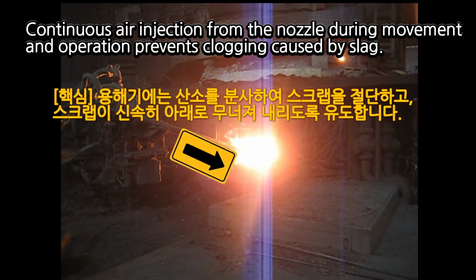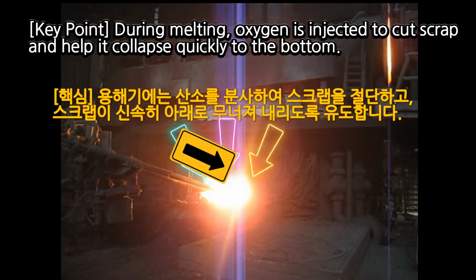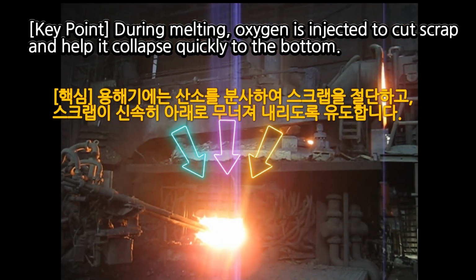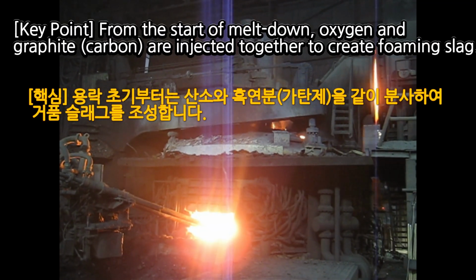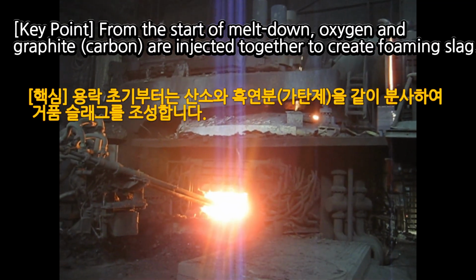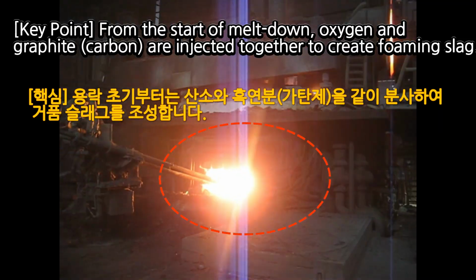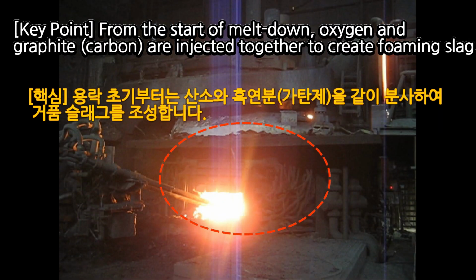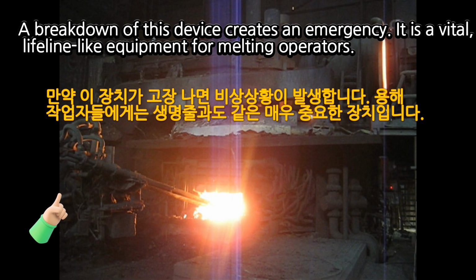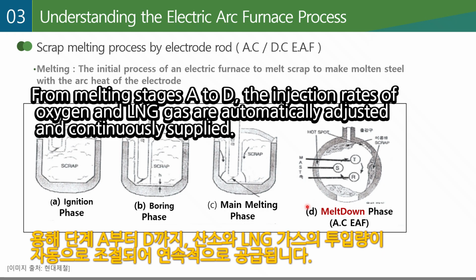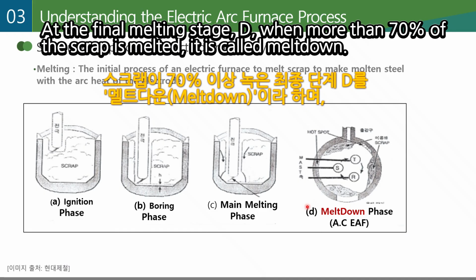Continuous air injection from the nozzle during movement and operation prevents clogging caused by slag. Key point: from the start of meltdown, oxygen and graphite carbon are injected together to create foaming slag. A breakdown of this device creates an emergency. It is vital, lifeline-like equipment for melting. From melting stages A to D, the injection rates of oxygen and LNG gas are automatically adjusted and continuously supplied.